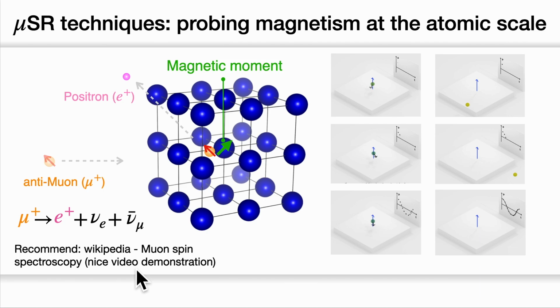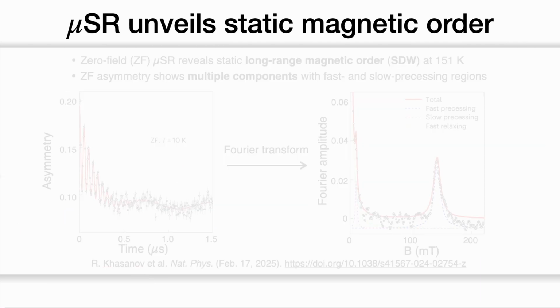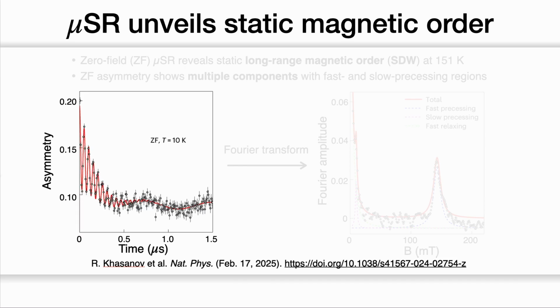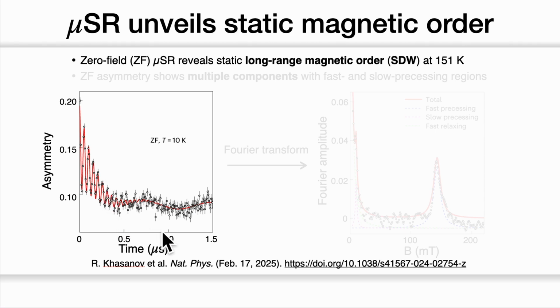Anyway, in the next slide, I'm going to show you the real data for the LNO superconductor. Here shows the result from muon spin rotation measurements. Asymmetry means the correlation between the spin direction of implanted muon and the emission direction of a positron. We can see an oscillatory curve, which means the material has a static long-range magnetic order, that is SDW.